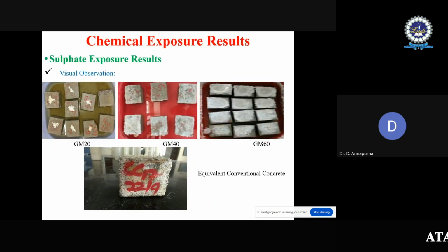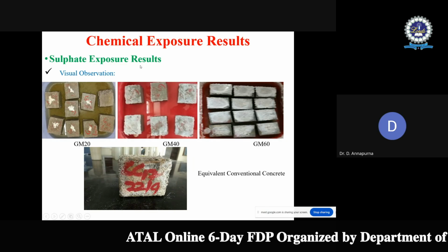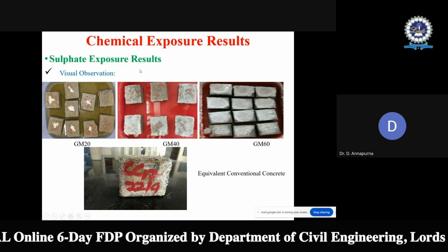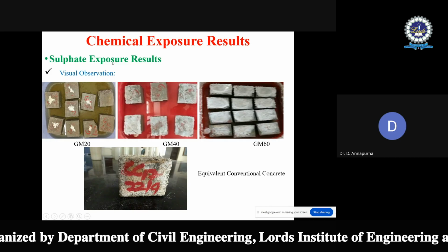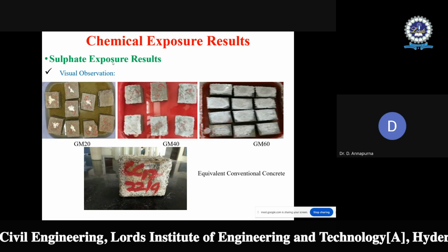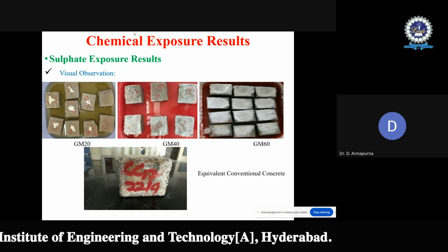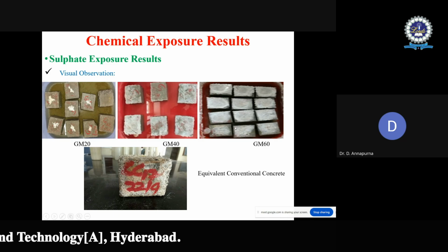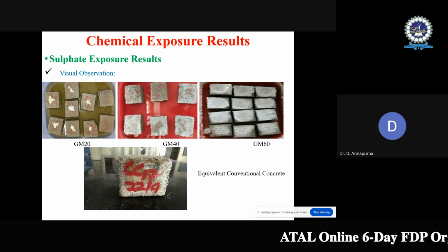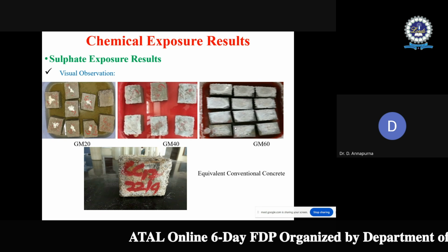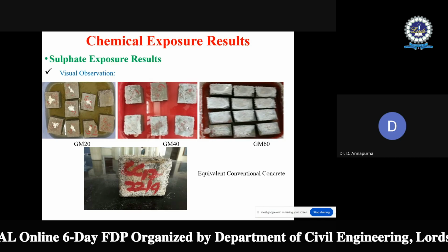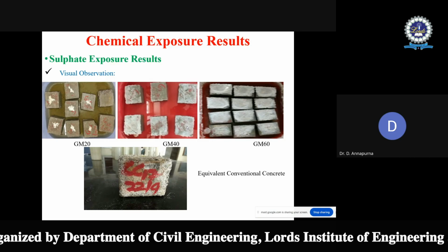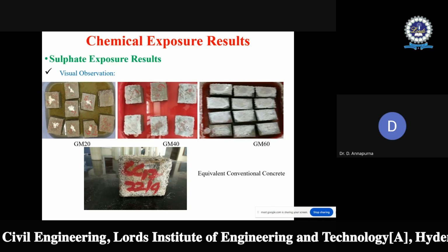Then chemical exposure. Here, first is the sulfate exposure results. Visual observation is seen here in the sulfate exposure. Two types of chemicals are used: sodium sulfate and magnesium sulfate. These are the specimens which are immersed in magnesium sulfate. It is observed that the impact of magnesium sulfate solution on the specimens is high compared to the sodium sulfate solution.